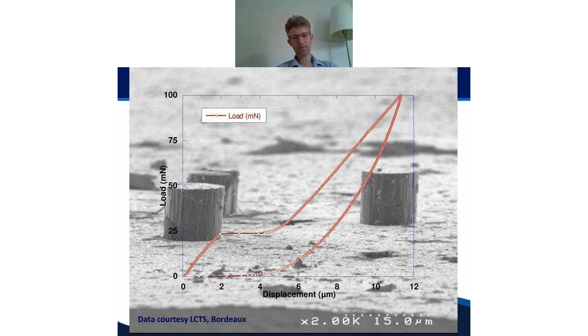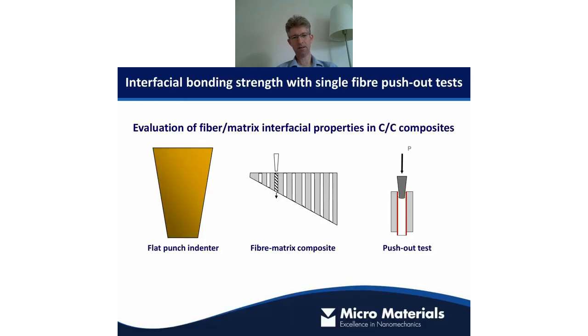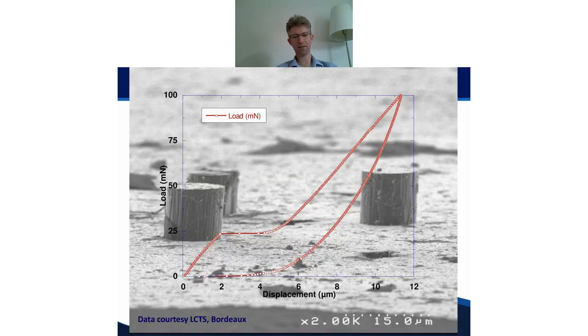So they can do this for different adhesion strategies for the fiber and pick the best bonding for the application. This is an example, an SEM showing the consistent way that these fibers have been pushed out. This is the back side of the sample. We also have the load displacement curve as we load up, and there's an abrupt yield here where the fiber slips, and then it recontacts again. As you can see, it's a flat end, but there's some geometry to the indenter, so as you push down, you recontact further up. Both of these features you see very nicely in the data.